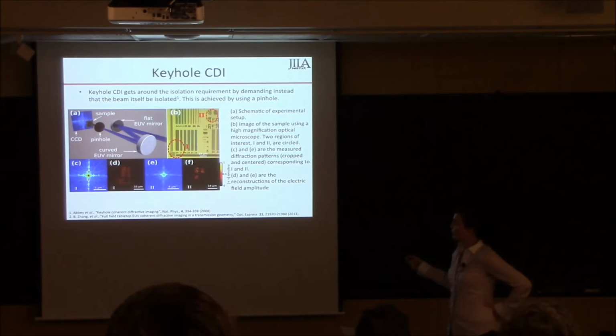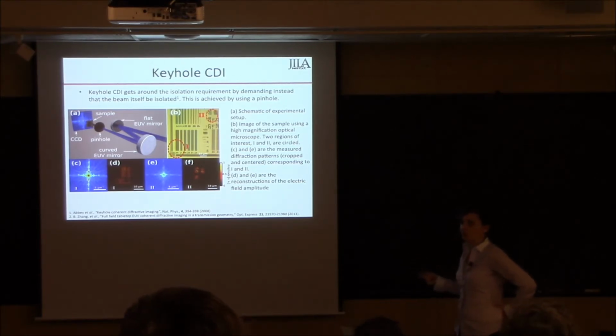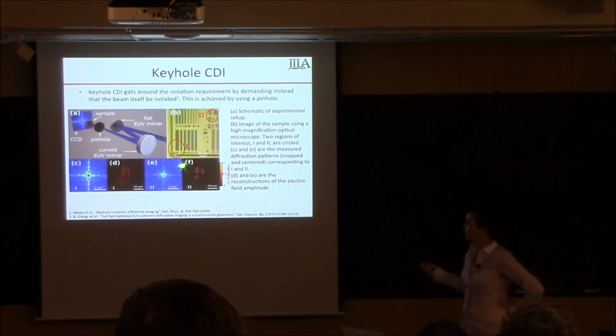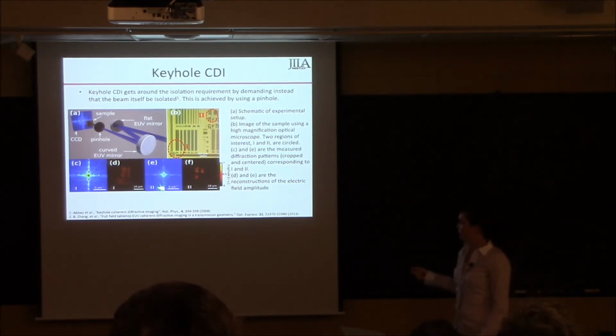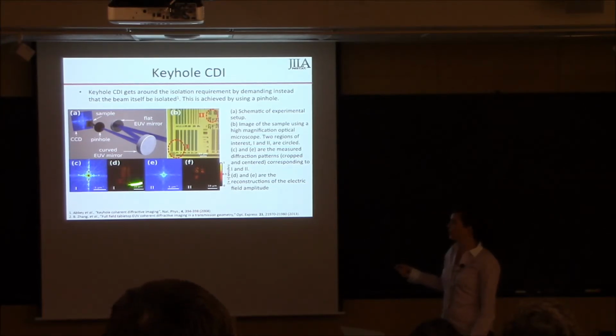And this is an optical microscope image of the sample that was used. And you can see two regions of interest. Regions 1 and 2 are circled. And down here we have two diffraction patterns that correspond to these two regions, and then two reconstructions that correspond to the regions.